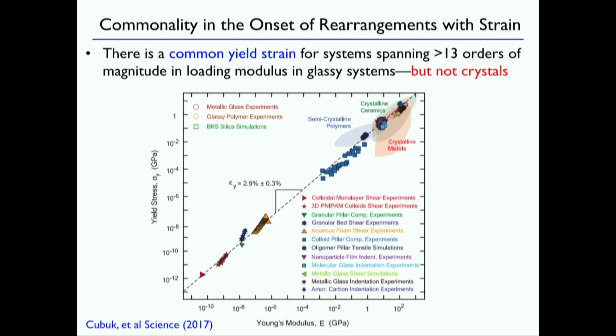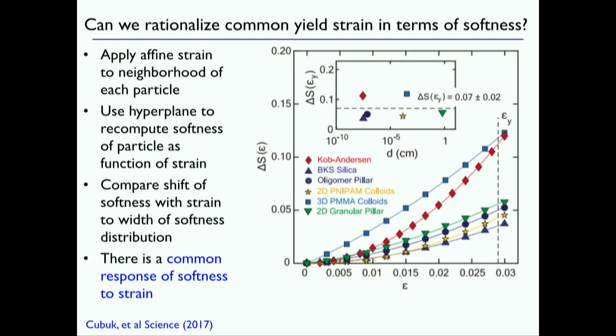The yield stress turns out, for disordered systems, we looked at 13 different systems spanning 13 orders of magnitude in the elastic moduli. So really different systems, and they all had roughly the same yield stress, about 3%. And that corresponds to a change of the softness. How much does the softness have to change at the yield stress? That is roughly the same for these different systems. So softness actually tells us something about the yield.